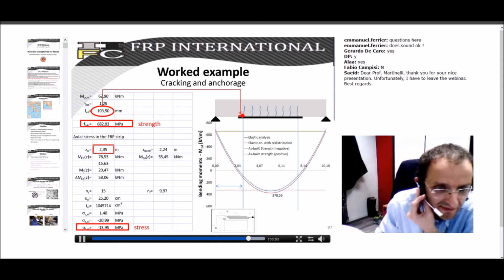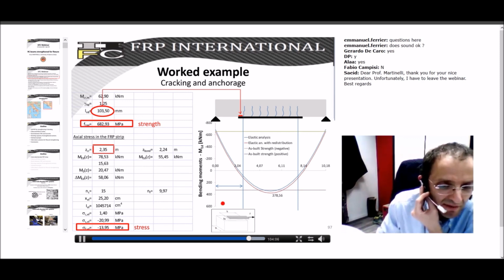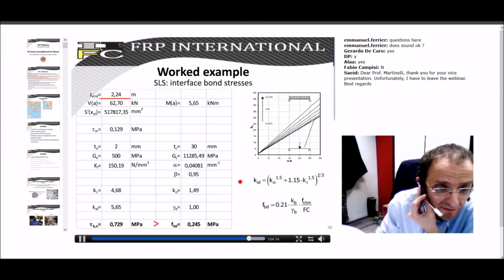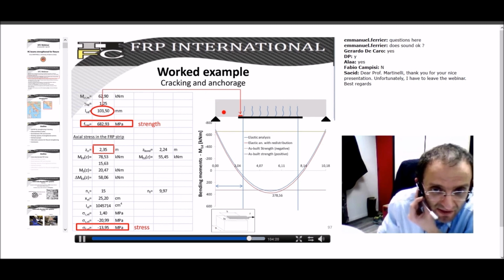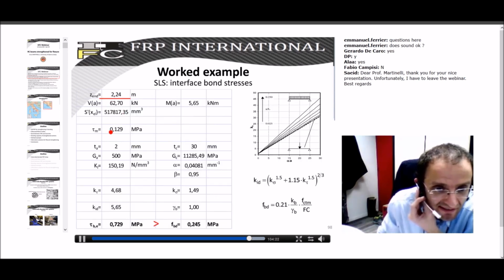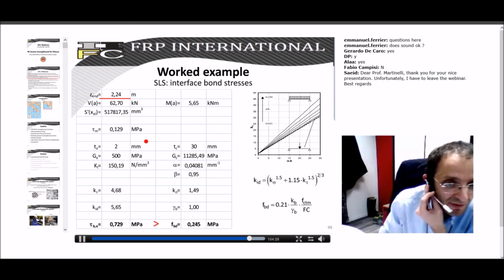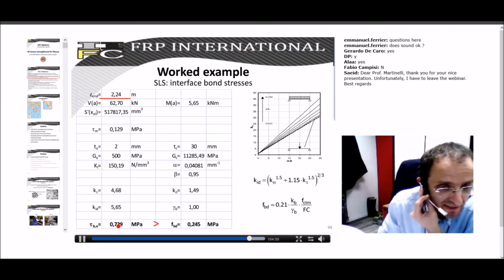Then we can provide this strengthening with just this length, and we are sure that the stress in the FRP strip is far below its maximum strength. So we have avoided the end debonding, but we have also taken into account the service load. So we have a certain distance A from here to here, and this will result in a certain value of KID and a certain value of tau evaluated for the service loads.